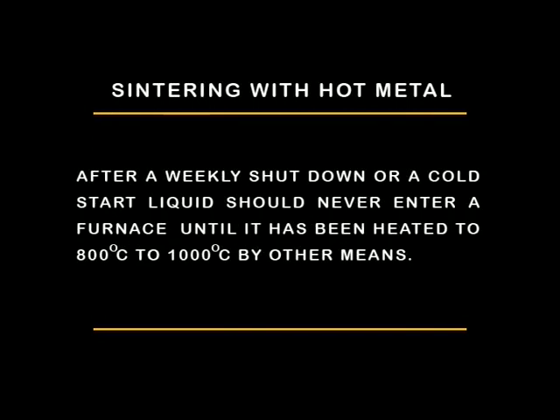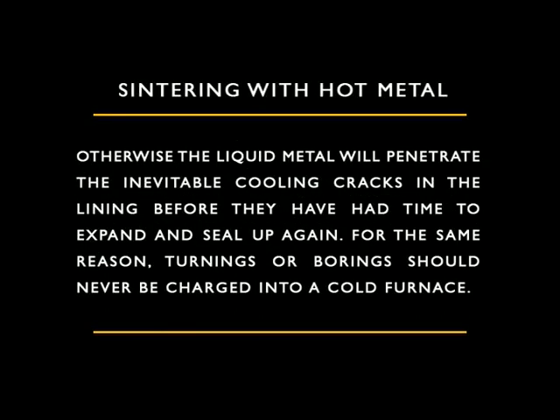After a weekly shutdown or a cold start, liquid metal should never enter a furnace until it has been heated to 800 to 1000 degrees centigrade by other means. Otherwise, the liquid metal will penetrate the inevitable cooling cracks in the lining before they have had time to expand and seal up again.